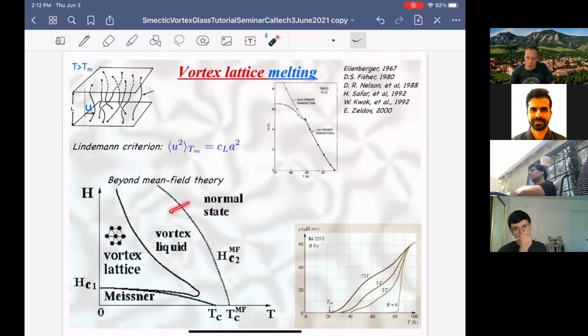And while the original HC2 line is just a mean field crossover line, it separates a vortex liquid, where the vortices, or fluctuations of the superconductivity order parameter, are in a nonlinear regime, so you can identify vortices. Beyond this, the vortices are overlapping, so you would call that a normal state. There's a typically fairly sharp crossover across this mean field line, but qualitatively, this vortex liquid is indistinguishable from the normal state.